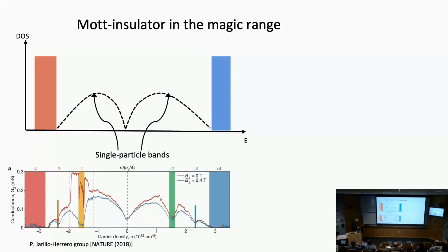system come from. So the theory that I just told you about basically gives us density of states as a function of the energy. These are the single particle bands that we calculate, the flat bands, separated by gaps from the rest. And this is the corresponding experimental picture. Red and blue shaded regions are zero conductance ranges where there's no states. So these correspond to band gaps.